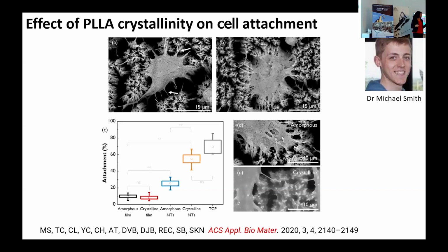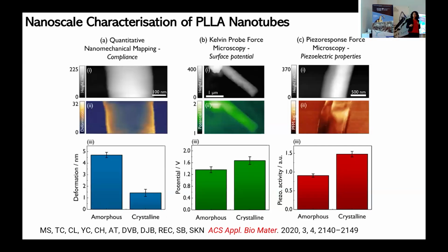So what exactly are they responding to? What they're responding to is two main things. One is the stiffness of the material. With the crystalline nanotubes, one would expect them to be stiffer. We use a method called quantitative nanomechanical mapping. It's an AFM-based method by which you use the tip to deform the material to see how stiff it is. The further you deform, the softer it is. Here are amorphous nanotubes, here are crystalline nanotubes, and you can see that the amorphous ones are more easily deformed, which means that the crystalline ones are stiffer.